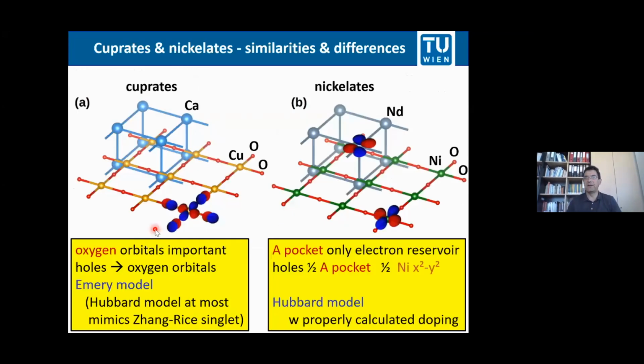That means altogether we arrive at the following picture. On the left, you see the cuprates. We have the x squared minus y squared orbital, but we can't forget about the oxygen orbitals. The holes go into the oxygen orbitals, and we need an Emery model. The Hubbard model might only serve as an effective model in the case of the cuprates. For the nickelate, the oxygen orbitals are further down. Also, the A pocket and the 4f are not really important. So we can live with only the x squared minus y squared orbitals. Of course, the hopping from one nickel site to the next is still mediated by the oxygen, but only virtually. No real holes go to the oxygen.